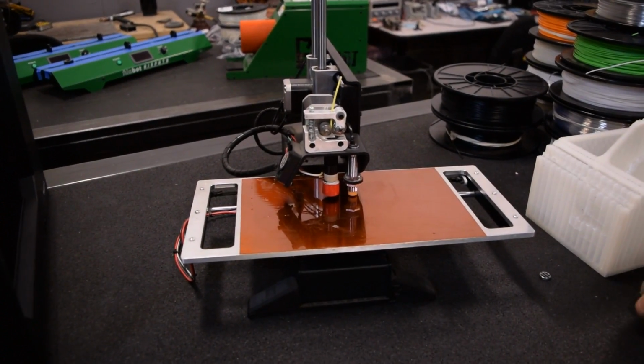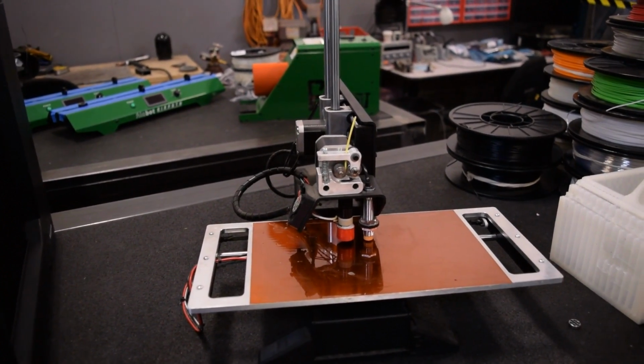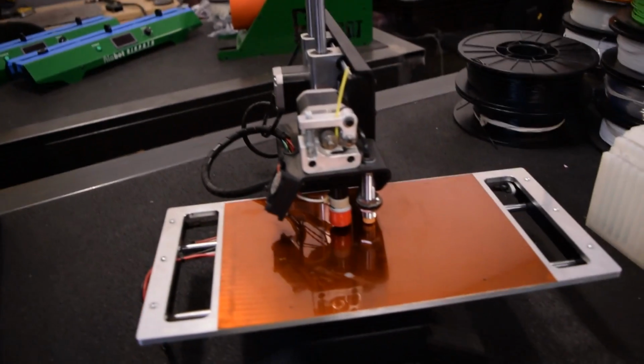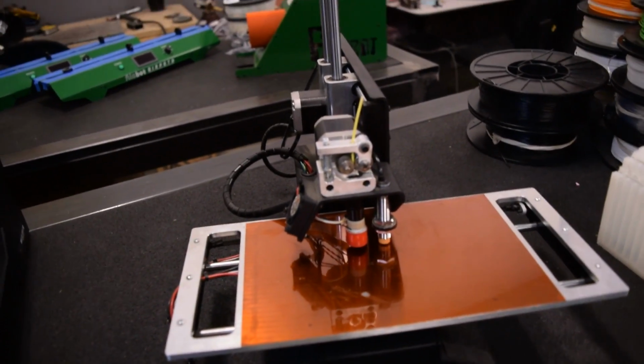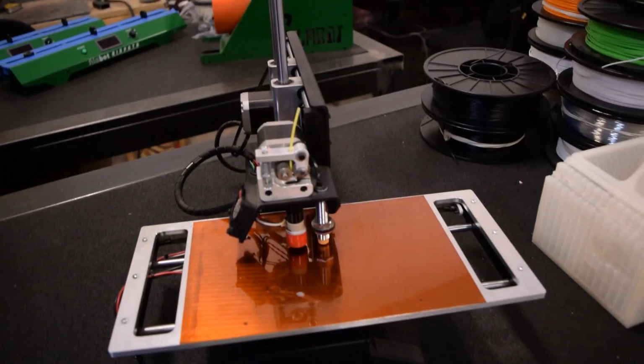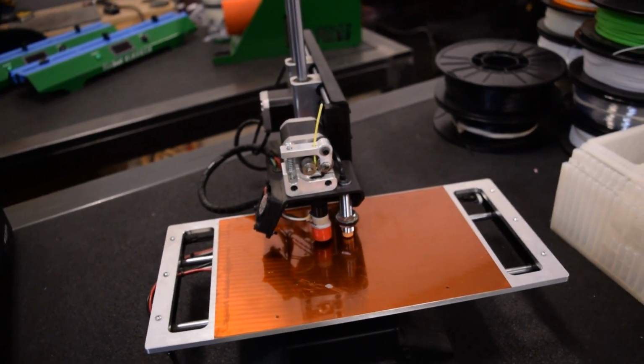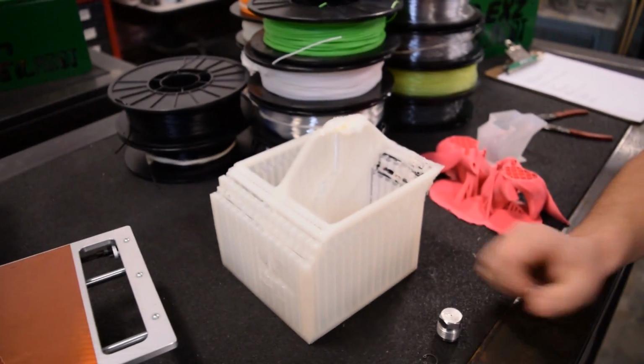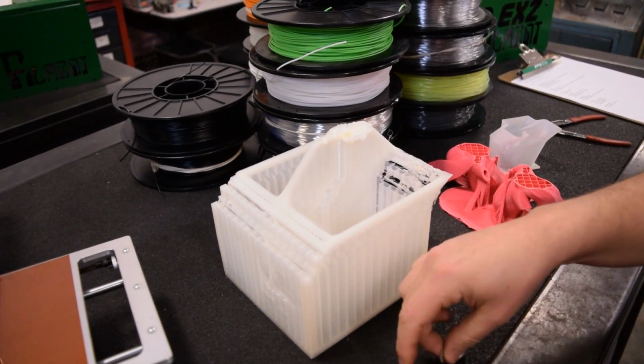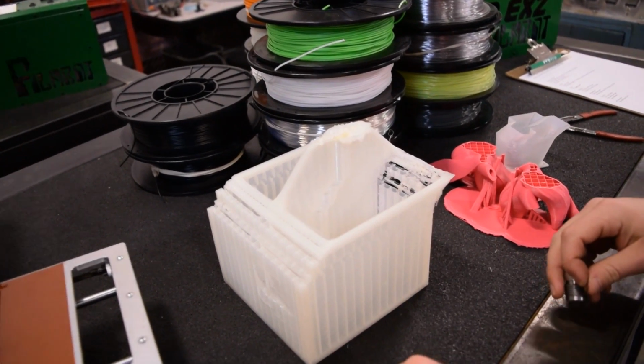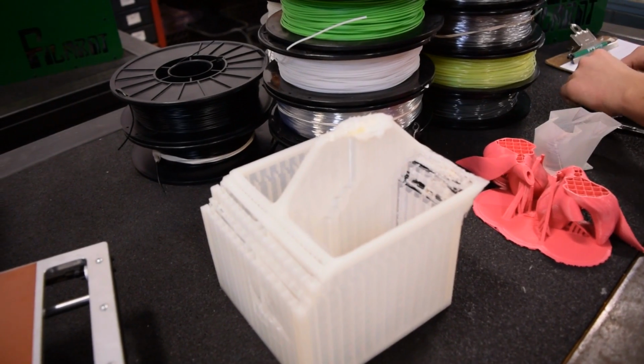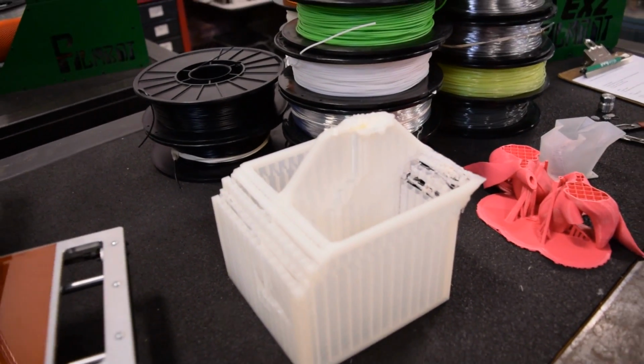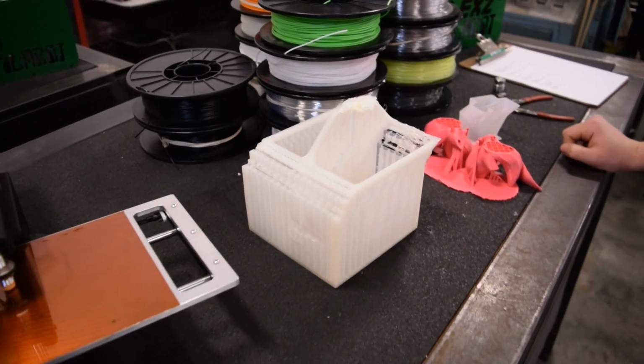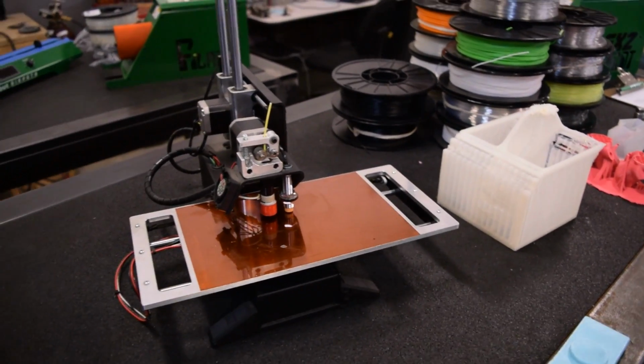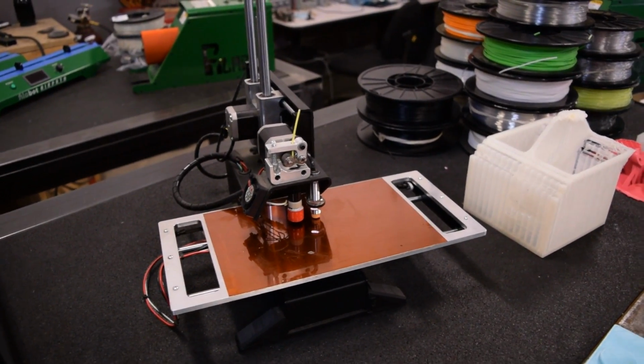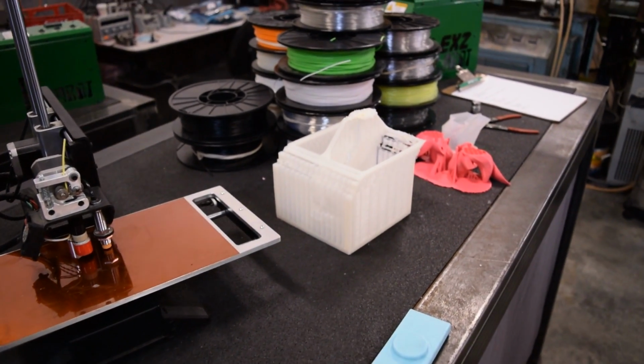Yeah. So another issue is temperature, and that kind of ties into warping too. So if your temperature is really high on your print, that's going to cause more thermal expansion, which in turn is going to cause more shrinking, and that's going to cause your part to warp more. So you want to extrude just at the melting temperature of the polymer, so that you're not going to cause too much warping.